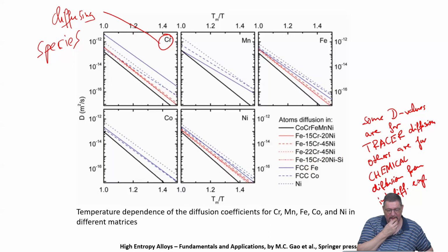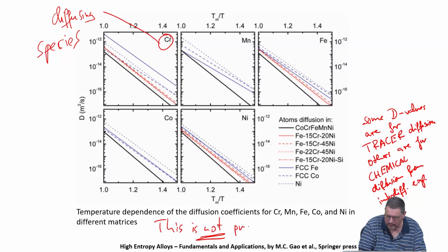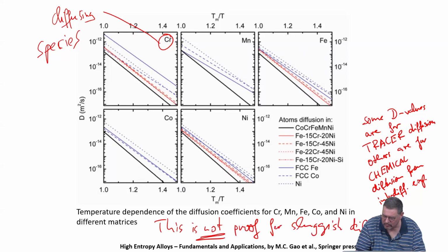Also, if it is within 1 order of magnitude difference, like in most cases here, it's very difficult to say, because you have an error bar also, which is not shown here. So it means, I would say, this is not proof for sluggish diffusion. Right, so one needs to do better.